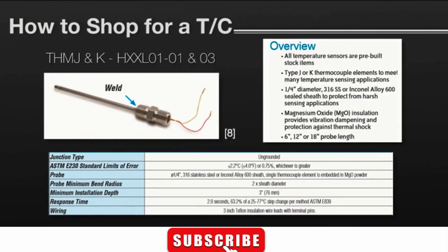Let's find the thermocouple probe online. This straight probe from Automation Direct has a pipe plug on it for screwing it directly into the wall of a furnace or an oven. You can buy it as a type J or K calibration with a 1/4 inch, that's 6.3 millimeter, outer metal sheath made of either 316 stainless steel or Inconel. Both of those sheath materials do stand up very well to the corrosive environment of a furnace.